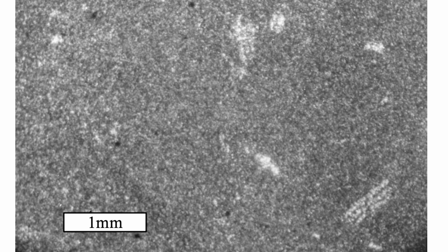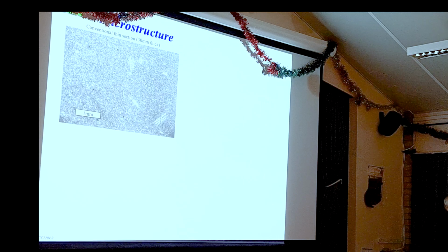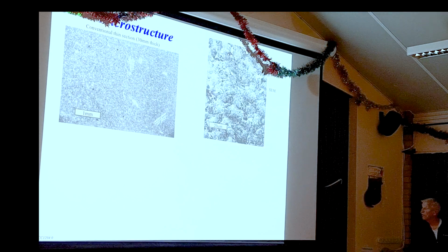And the problem there is the flint is made of very, very fine grains. They're just a few microns across. So if you've got a 30-micron thick section, you're looking at maybe 20 or so individual mineral grains stacked up. I did, as part of my research, try and grind some little wafer thin sections, and then you can start to see a bit more, but it doesn't help very much. But if you can't see much down an optical microscope, you have to go up a stage, and what we do is we go to the electron microscope.